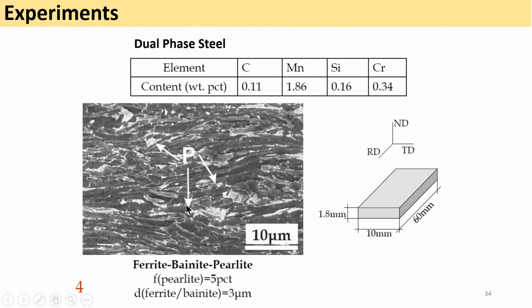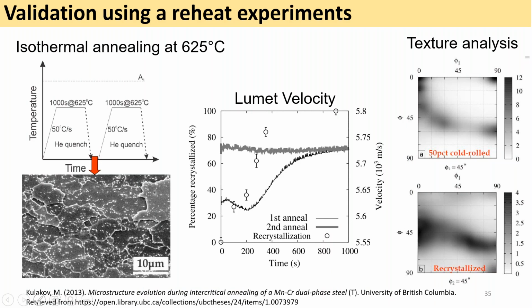These are the initial microstructure of this dual phase steel with the composition. Again, this is a microstructure composed of ferrite, bainite, and pearlite. And what we can see here is this variation of velocity during the recrystallization. Same as before, we have a sharp change in velocity during the recrystallization. To convince ourselves that this change in velocity is actually due to the recrystallization occurring in the sample, we reheated the sample a second time from the recrystallized state, and we can see that the velocity did not vary